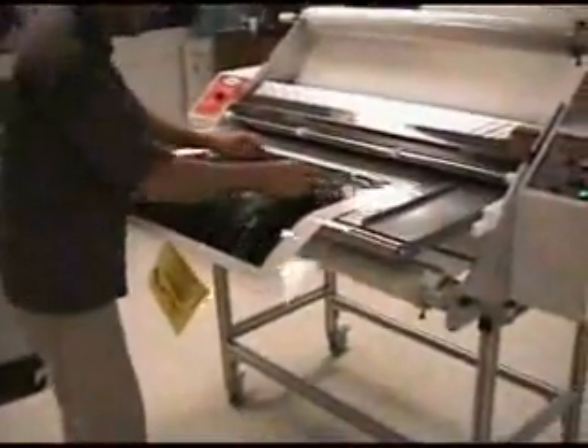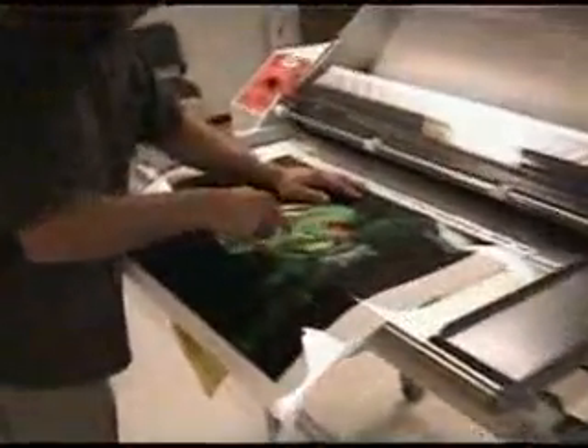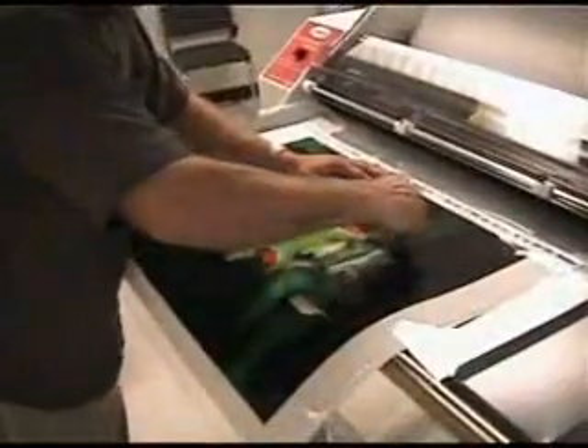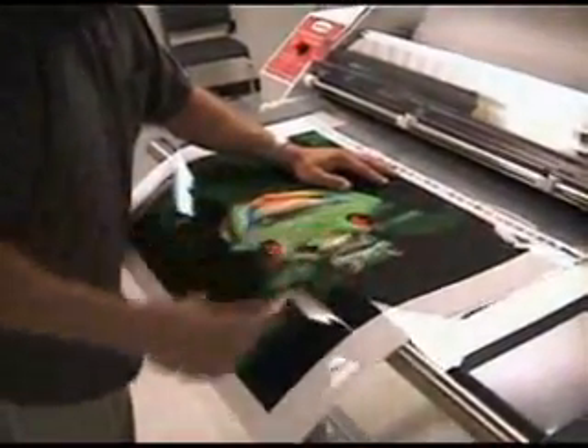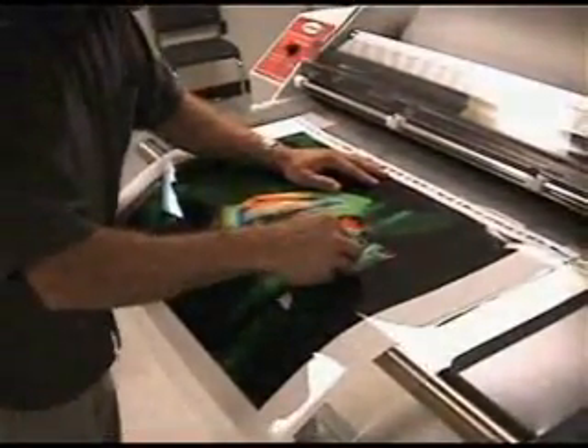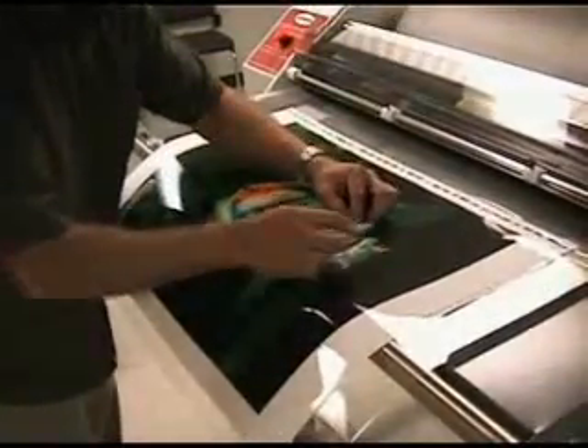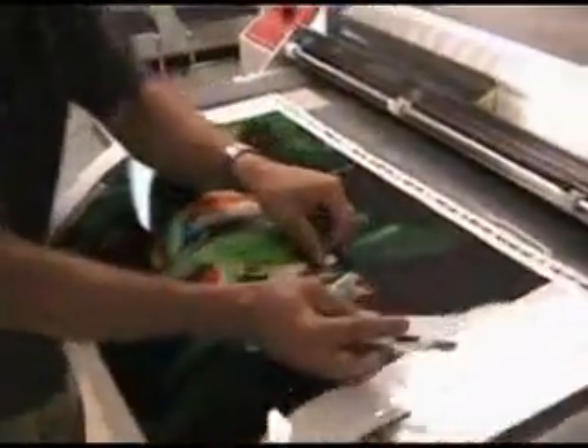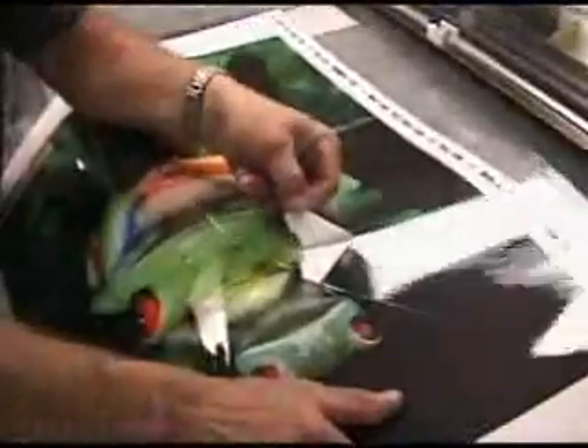To determine how well your laminated piece has adhered, we will perform what is known as the X test. Using a utility knife, score the top of the laminated piece in an X pattern. Lift the edge and pull back. If you lift ink and paper fibers as you pull back, you have a good bond. If you pull back the laminate with no resistance or without lifting ink or fibers, the lamination is not good.